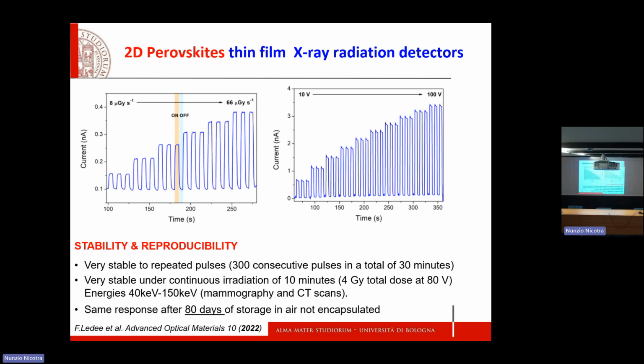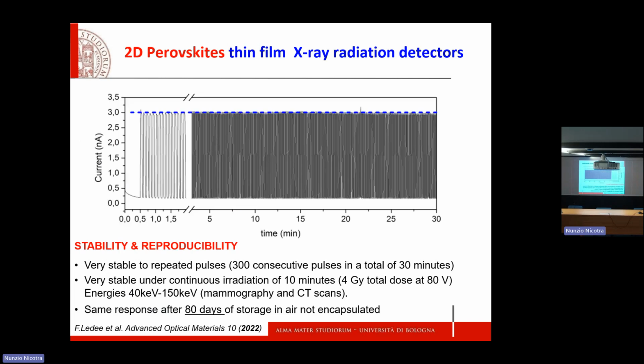And whatever you induce with your injected carriers is a huge signal, because you always measure the delta I over the I. If the I, the dark current, is very low, any delta I produces a fantastic signal to noise ratio. And here you see how nice this on-off switching signal is and how stable it can stay. It is very stable under the typical irradiations that we use for mammography, and it has been stable also after 80 days of storage in air without encapsulation.